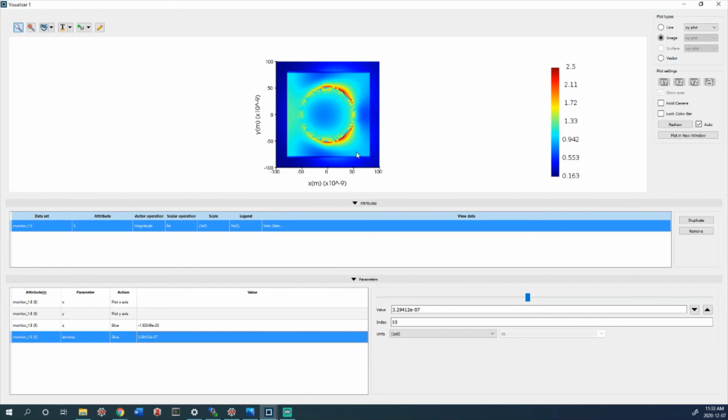What's also happening is we're actually reaching the scattering resonance of this nanoparticle. So if we kind of go back here, all right, let's look at the scattered field. All right, so that's the region of where the electric field is lower. So the only field in this region around the outside is the field that is scattered from the particle. Now if we go down, we actually see that the scatter field increases in these lower wavelengths. So we get a scattering resonance. And we actually expect that for a 50 nanometer silver particle, we expect that to be around 300 nanometers.